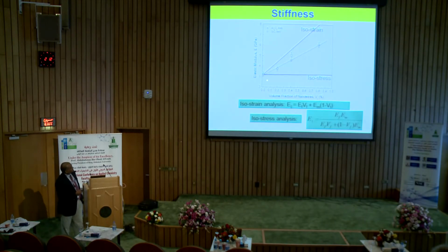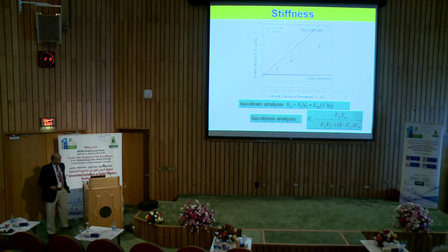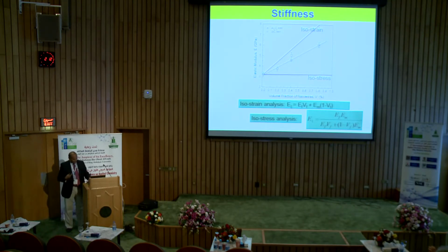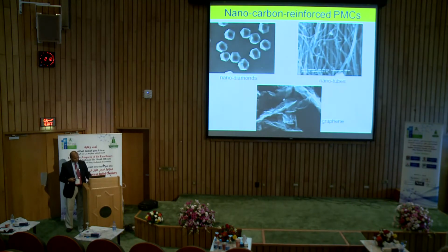So here I just show you the elastic modulus as a function of volume fraction of the nanowires that we put in the polymer. Because this is a very dilute concentration, a flat line is what is expected, but you see quite a dramatic increase in the properties. This is because of the large surface to volume ratio.